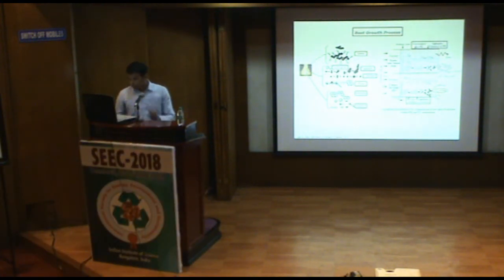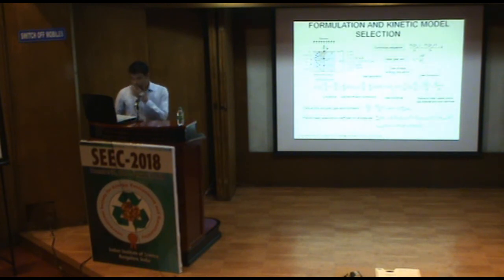So here, a conceptual illustration comparing the soot growth process within a porous burner and free-flame combustion is shown. Here you can see that a porous burner not only reduces carbon monoxide, it can also suppress soot generation. It delays the soot formation process and aggregate formation process. The final soot volume fraction and soot particle sizes at the burner exit are low in the porous burner as compared to free-flame combustion. So this is the present computational domain.